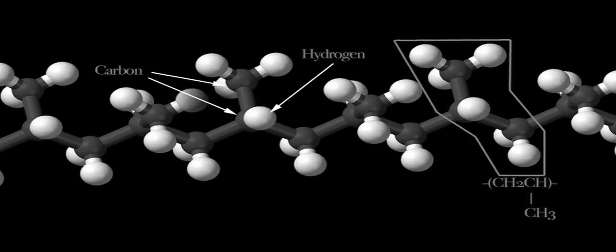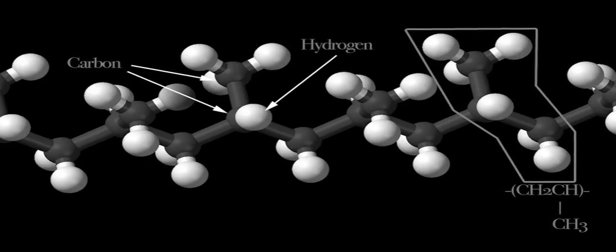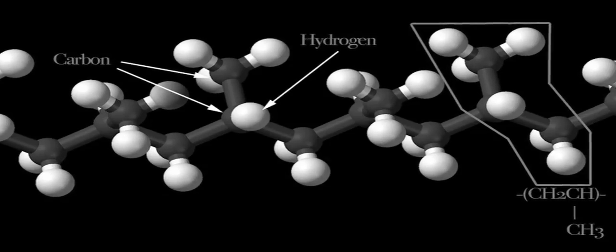Right. Now the question is, why is it called isotactic? Well, that's because Nobel Prize winning scientists, Natta and his colleagues, discovered catalysts which would make it so that these methyl groups always went on in the same way when you went up the chain. And they were called isotactic. It means sort of equal inclination, basically. So they're all arranged in the same way. So that gives the material a regular helix. So it makes it regular.